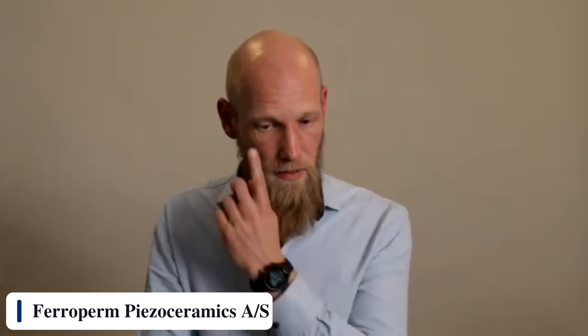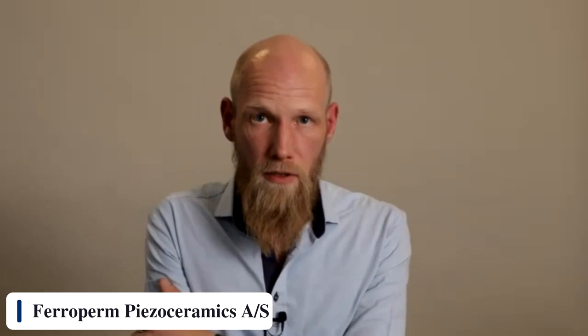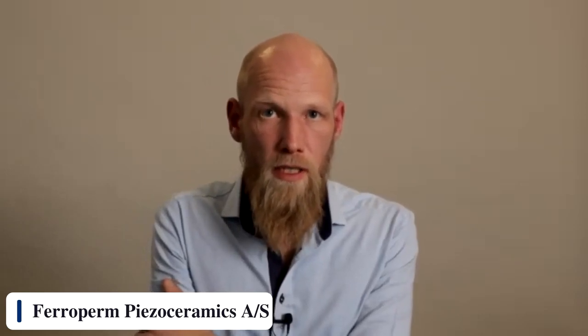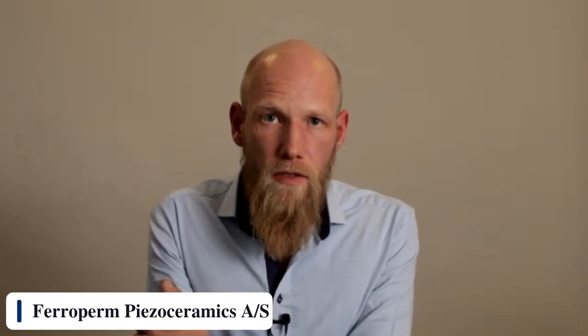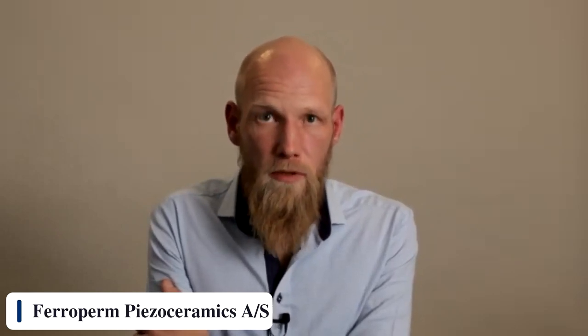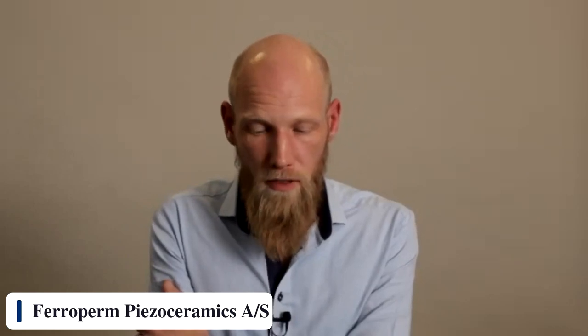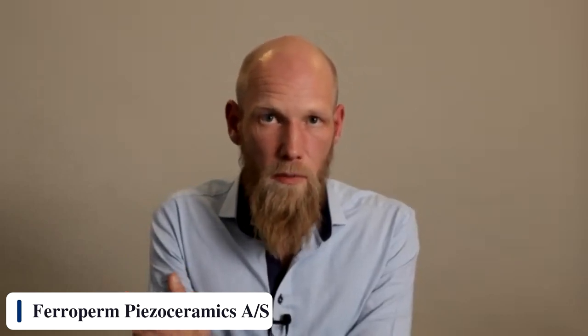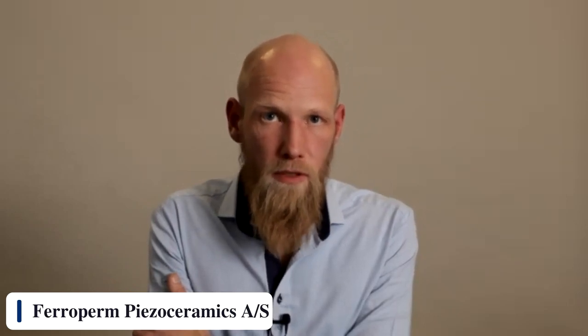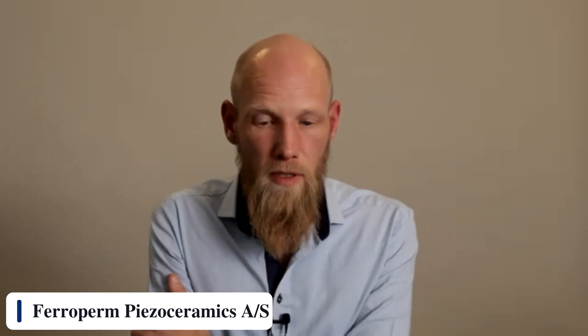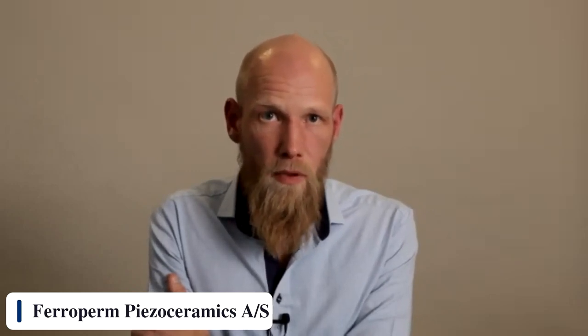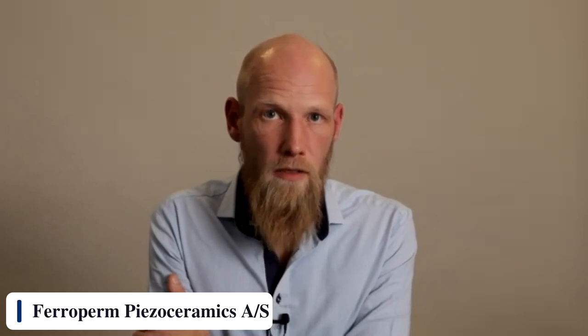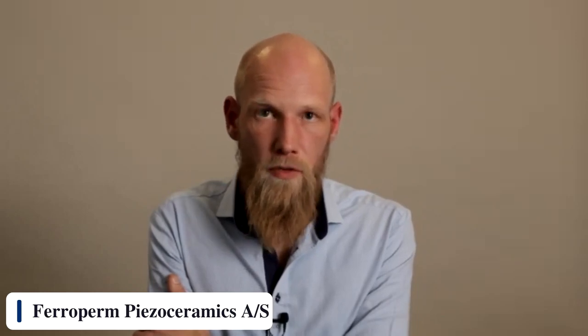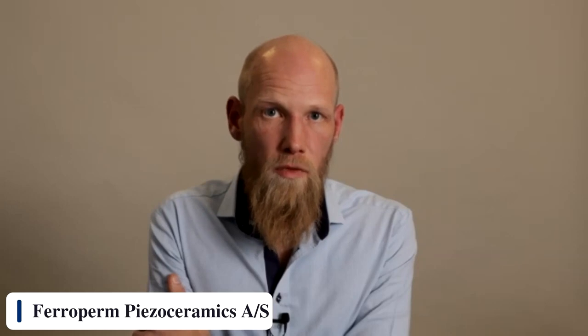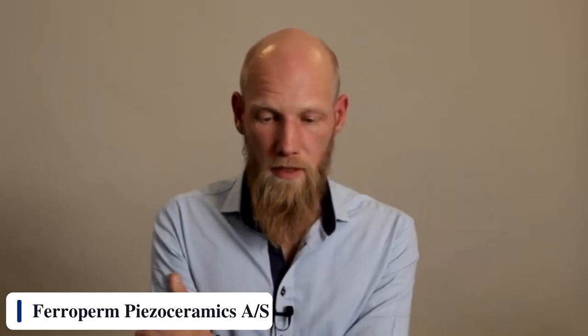Okay, so there's a question about high voltage polarization after curing the PiezoPaint. Yeah, so that's a requirement. It's still a ceramic material that is suspended in an organic vehicle or in a polymer, so you need polarization. The domains will still be randomly oriented when you apply the PiezoPaint. So there's a poling step, and the requirement for the poling voltage is higher than for ceramic, because you have the polymer basically screening the ceramic particles. So there's a bit of IP involved in that.